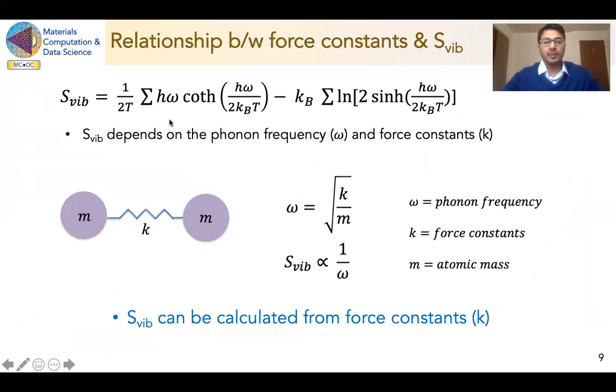Here's the expression of vibration entropy. And in this expression, omega, which is the phonon frequency, is the only unknown variable. And phonon frequency omega is dependent on two terms. One is K, which is the force constants of the bonds, and M, which is the mass of the bonded atoms. So the mass of the atoms is known, and with the computation of force constants of all the bonds, the vibration entropy can be calculated.